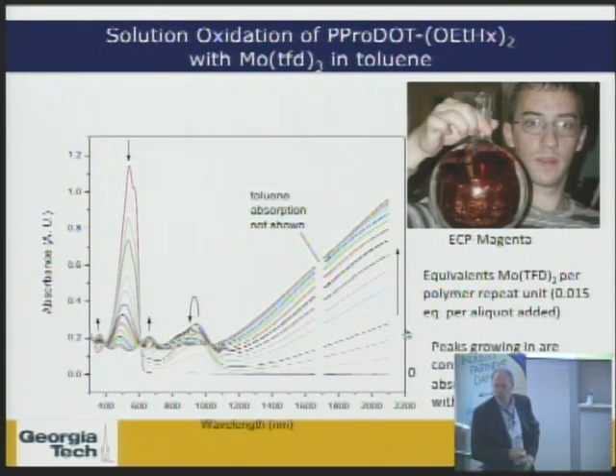The point of the interaction with Seth's group is the ability to oxidize this polymer. And what you can see is that the pi to pi star transition is in essence fully bleached, showing that this oxidant is extremely good for this polymer. And then we have a near infrared absorbance that is growing in during the oxidation process. In essence, this is chemical chromism that you're looking at right here.